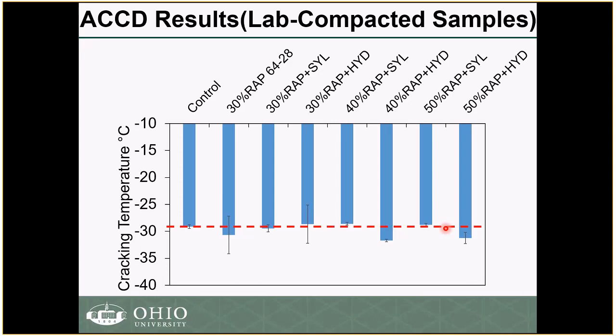For the lab compacted samples, again, it's the same exact thing, very similar results to the control, and again, this is in agreement with what we have seen in the lab, which is that the properties of your asphalt binder play a major role in terms of the cracking resistance of the asphalt mixture.